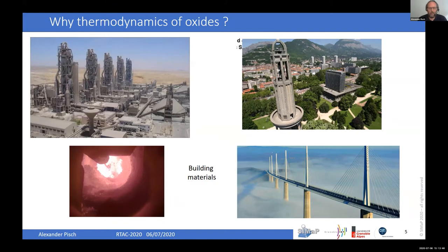Here, thermodynamics is helping us in two ways. On the left side, on the synthesis, it's a high temperature process. Natural raw materials, limestone, clay, sand, are ground and mixed together, and then put into a high temperature rotary kiln where they react and make calcium silicates and aluminates. It's clear that in the flame, which is close to 1600, 1700, 1800 degrees Celsius, equilibrium is not so far off. So having good data is very important in order to understand and to improve the process.